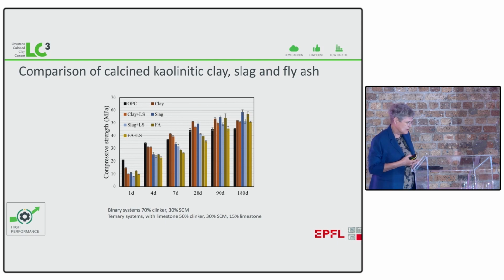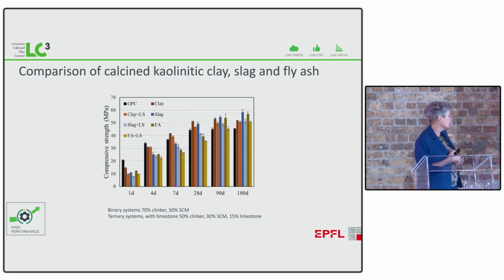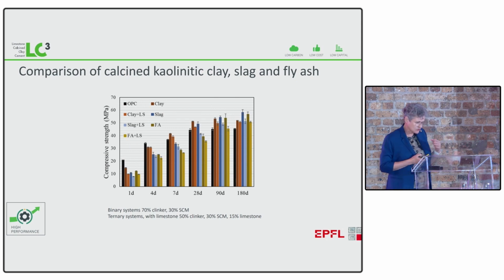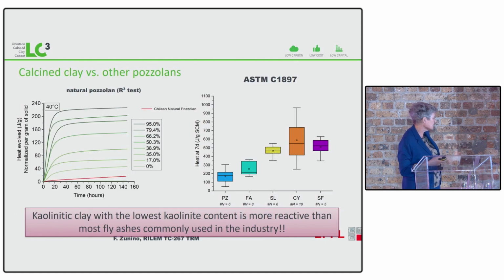And this is the very important comparison, because here we're comparing the mixtures made either with calcined clay, or with fly ash, or with slag. And if you look at the long ages, 180 days, you see all the strengths are pretty much the same. But what's particularly interesting about the calcined clay mixtures is they catch up the strength much, much earlier. So in this example where we've mixed everything together in the laboratory, it catches up at 4 days, but in some situations you can catch up earlier at 1 or 2 days.